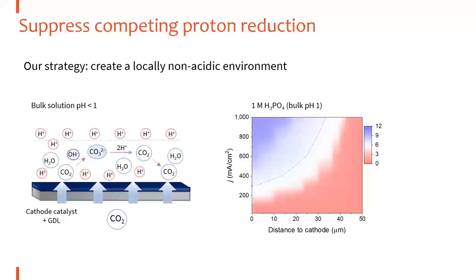We modeled our concept with a COMSOL-type modeling, and what we modeled is the pH around the cathode under different applied current density. Here the dashed line is the pKa of carbonic acid. If the pH is above this dashed line, CO2 has the chance to react with OH to become carbonate and bicarbonate. And if it's below, CO2 will be present in the form of CO2 molecules.